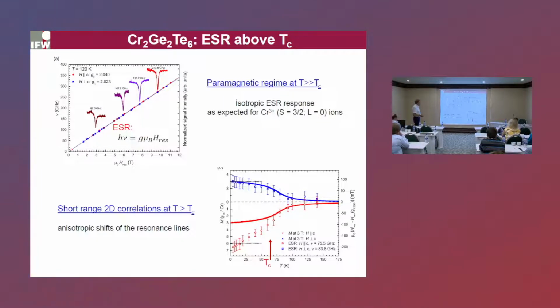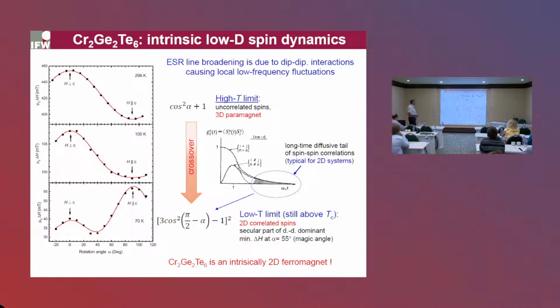The next evidence that this material is truly intrinsically low-dimensional, even in the bulk limit, is the angular dependence of the ESR line width. The ESR line width is given by the anisotropic dipole-dipole interactions, and therefore the width is affected by the relative direction of the applied magnetic field and some symmetry axis of the interacting spin system. And in the paramagnetic limit, the ESR response is given by the spin self-correlation function.